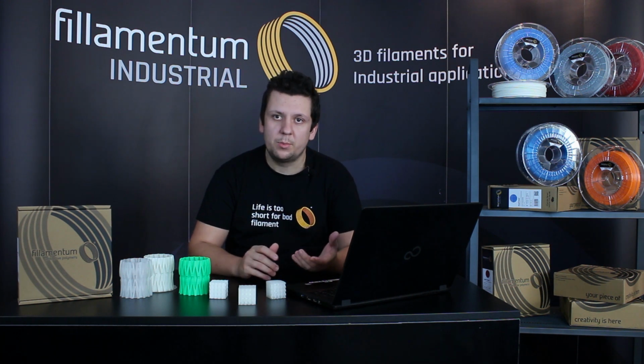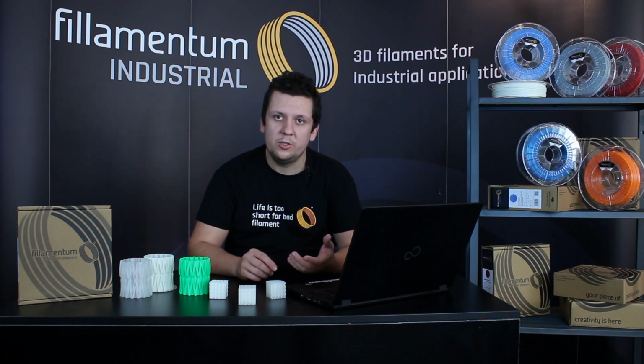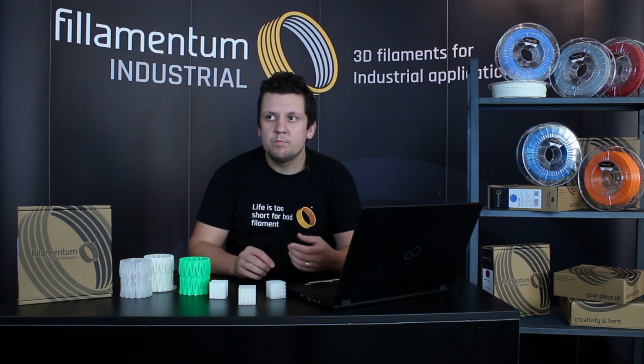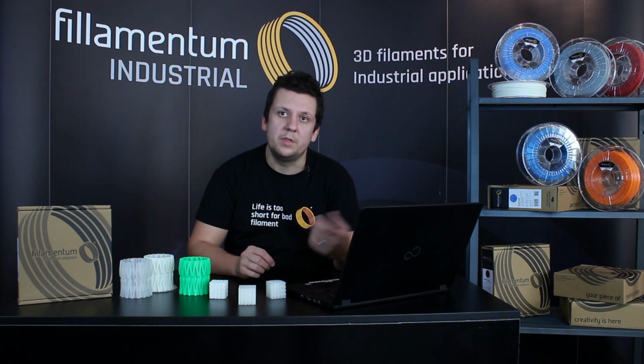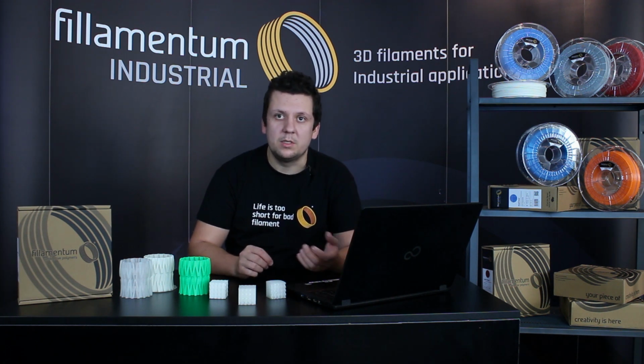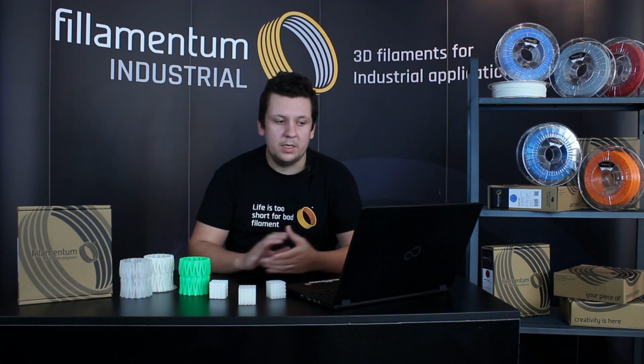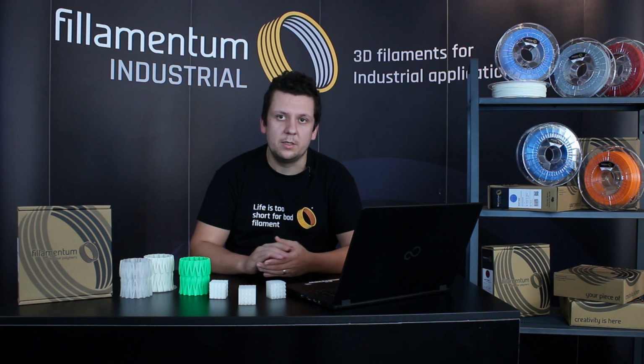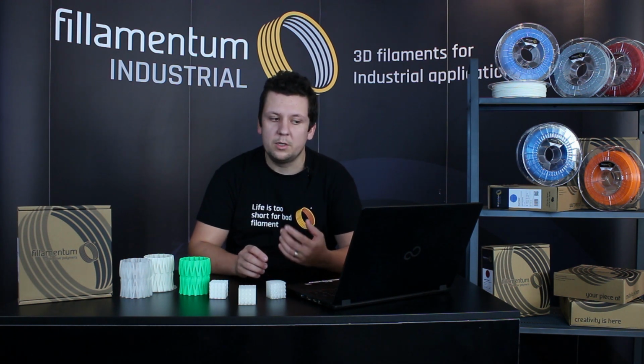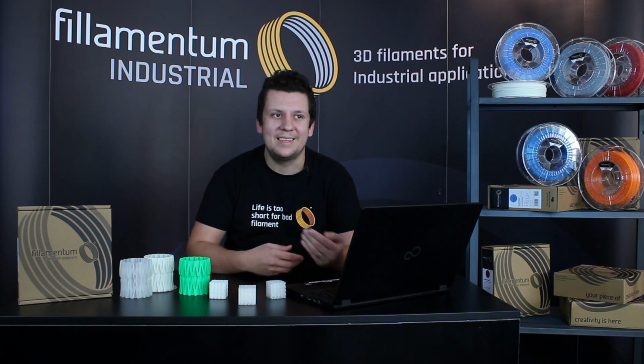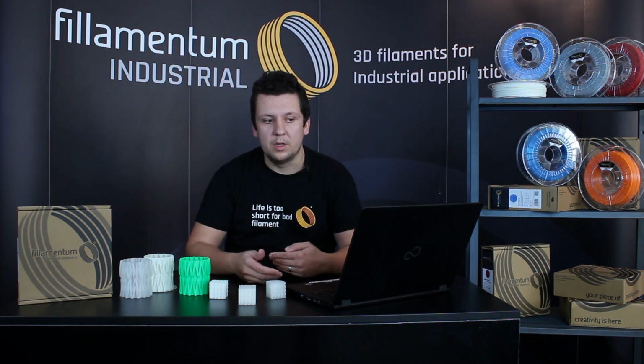The second one is tension. It's really important to release the pressure on the idler, because if you are pressing the flexible filament too much, it can be damaged and deformed, and it will be bigger, so it can run out of the extruder, and it results in failed prints. And the third one is retraction. For softer materials, I recommend turning off the retractions. If you have the harder ones like 98 TPU from our portfolio, we are printing with retraction on, so it always depends on your extruder.